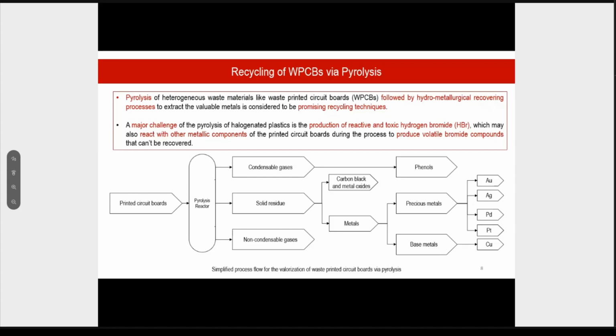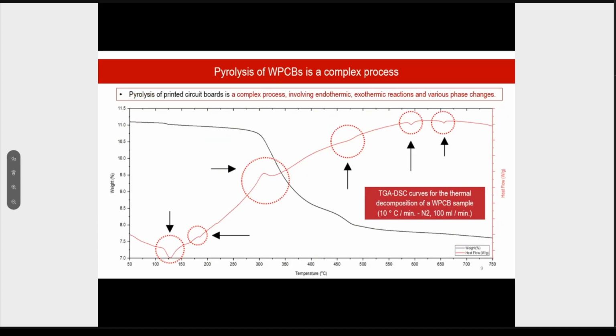We also have a challenge here, which is the generation of toxic emissions coming from the breaking down of the plastics. However, in these conditions at low temperature, we can study how we can control these emissions. However, we also have a big challenge here. As you can see, when we try to simulate the thermal degradation of printed circuit board using TGA or DSC, you can see different signals coming from this process, which involve endothermic reactions, exothermic reactions, maybe phase change too. So we have a big challenge here to understand fundamentally what is happening during this process.